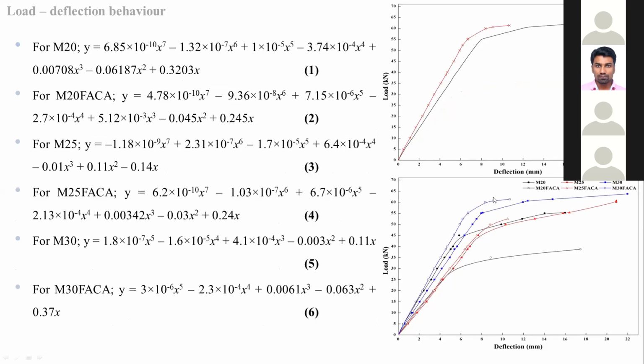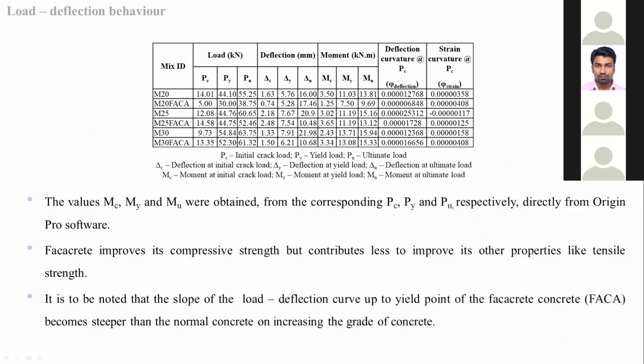And these are the regression analysis equations which were done on this experiment for each curve. Almost every curve has a unique regression analysis equation. And these are the values which we obtained from the regression analysis. And we found that even though Facacrete compressive strength is increased, its tensile strength is decreased. Facacrete is advanced more than conventional concrete in compressive strength, but it is deficient in the tensile part. So it is actually not a failed research. It is the beginning of a research, because we get a good result.